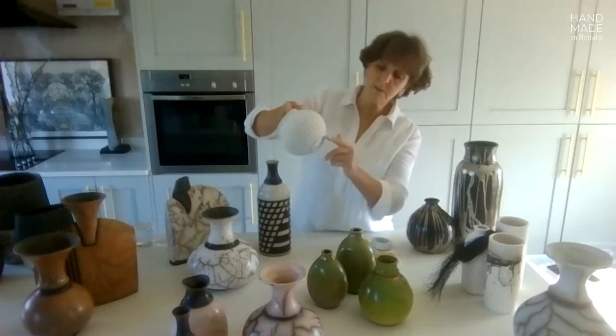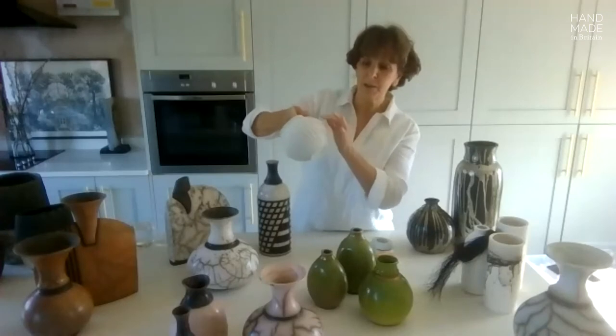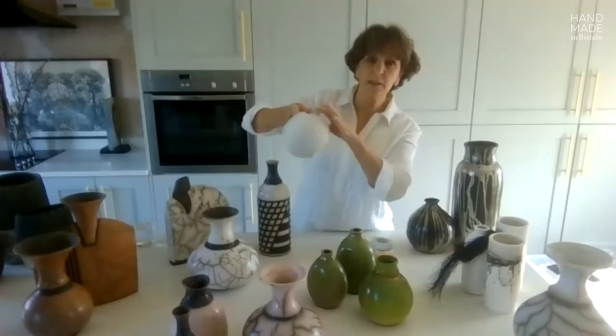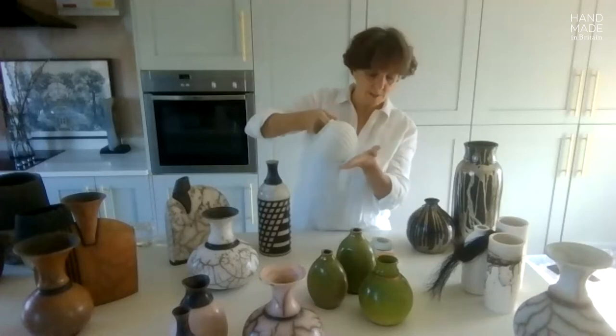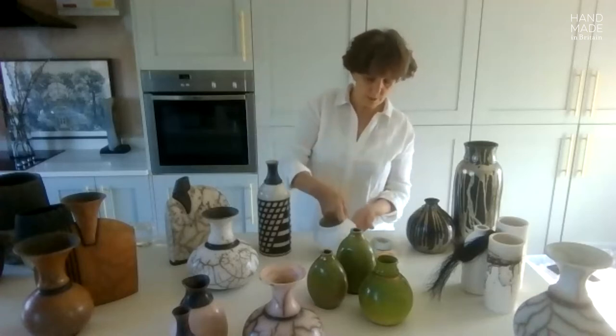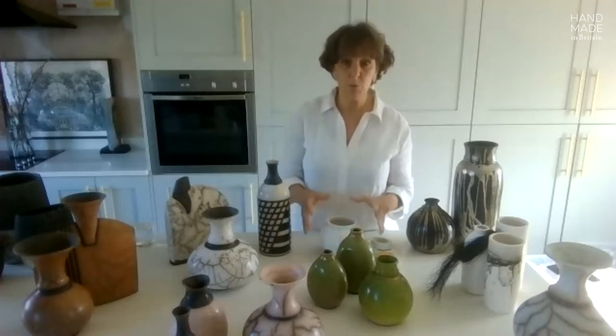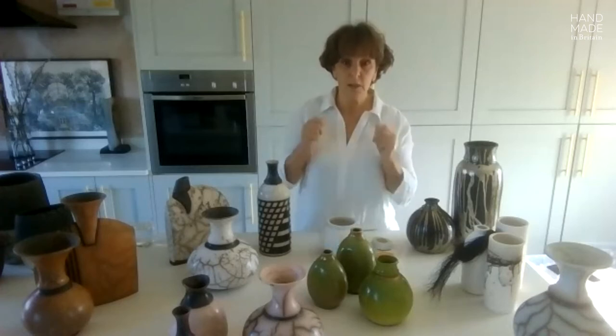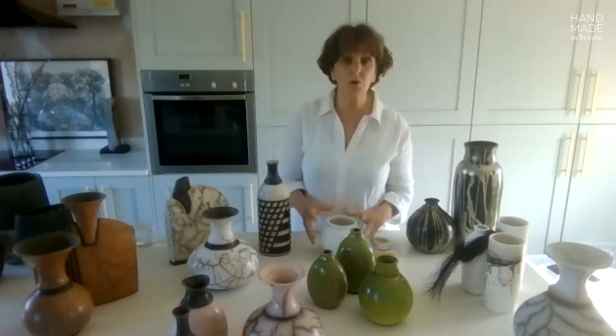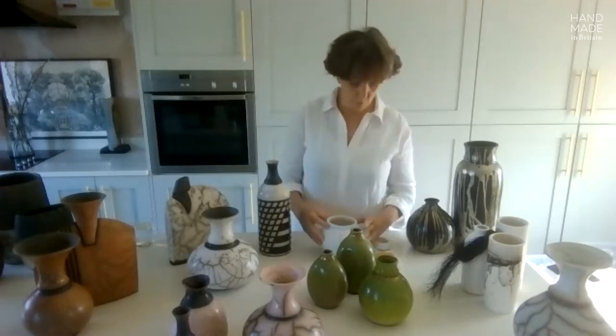All of these areas that you can see are blue will become black because the slip and the glaze are going to be the pieces that fall away. So that's the coating. It goes into the raku kiln, and this goes up to about 750–800 degrees. At that point the lid comes off the kiln, the pot is taken out with tongs and it's put into my sawdust pits. It stays in there for about 30 to 40 minutes, covered completely with sawdust.